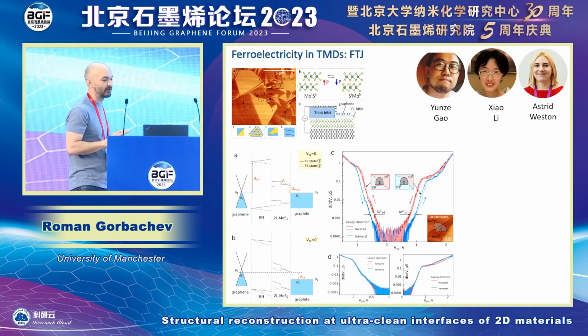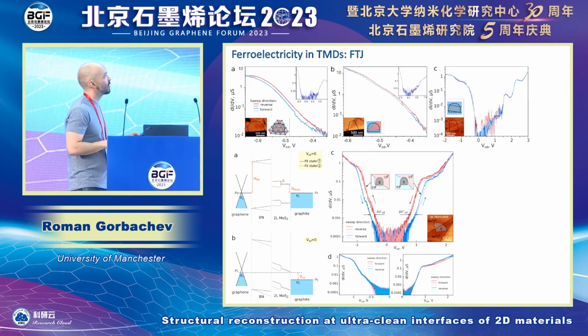So at the moment, we have aspect ratio of 10, but this can be improved further with design of the contacts and dielectrics. But that's not the issue. The issue really is that if you want to try different configurations where your tunneling junction is covering different domains, right? So here it is covering little triangular domains with a large twist angle. Here it is covering a sort of two-domain walls. You see the switching works differently.